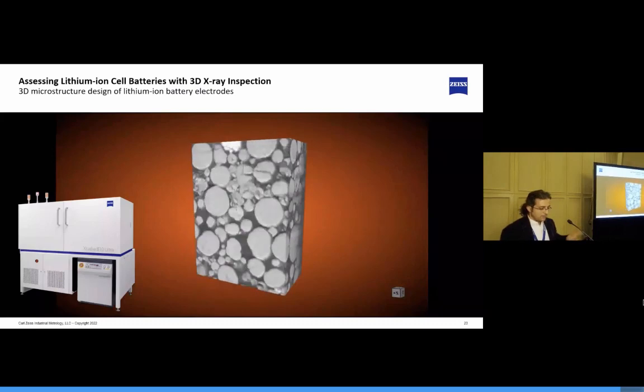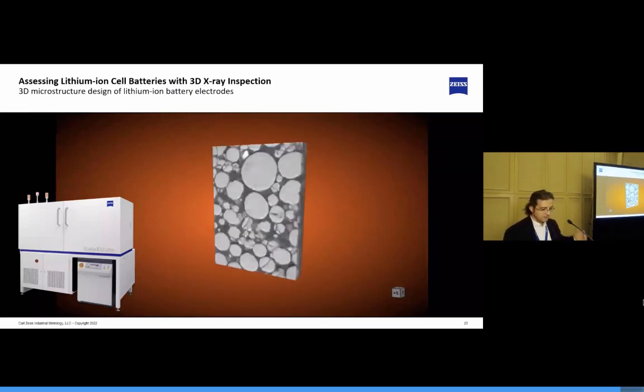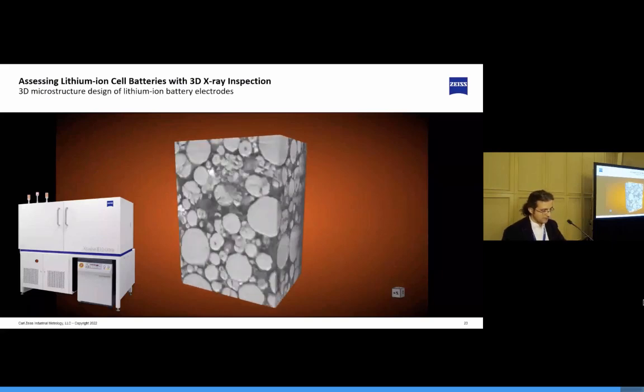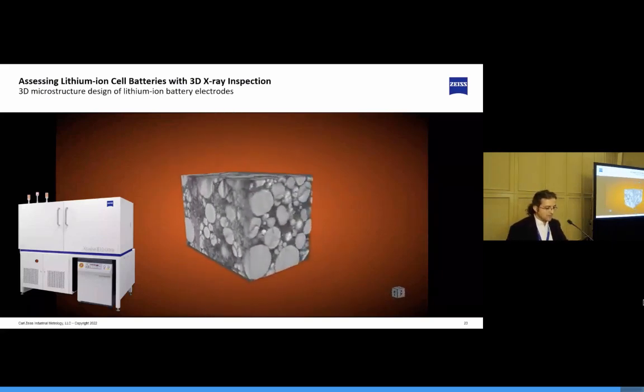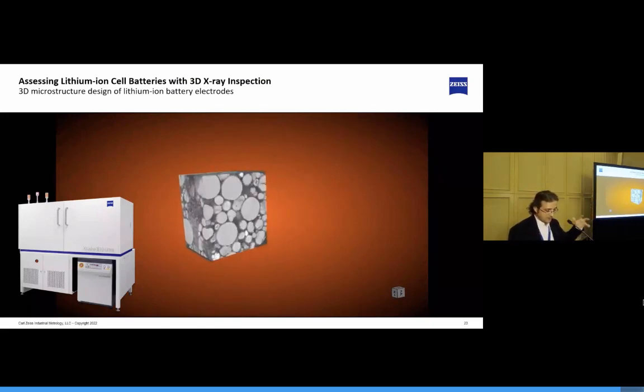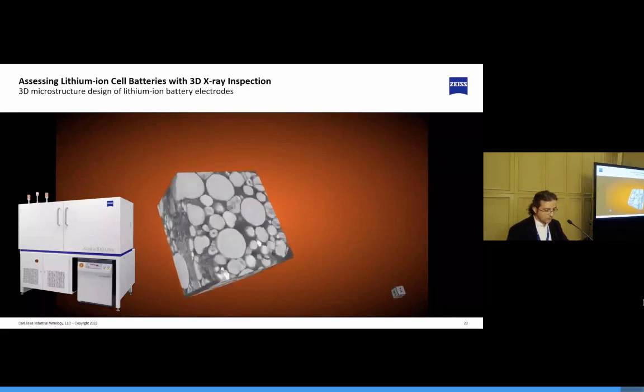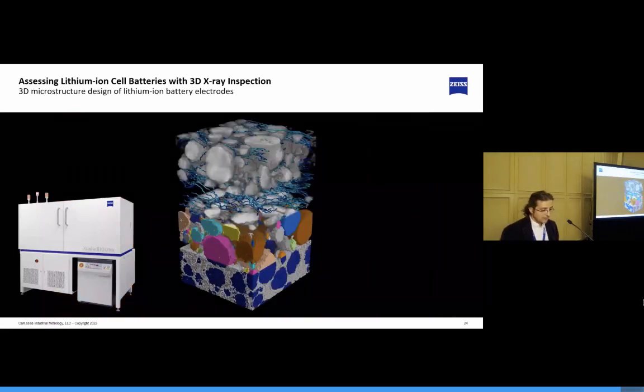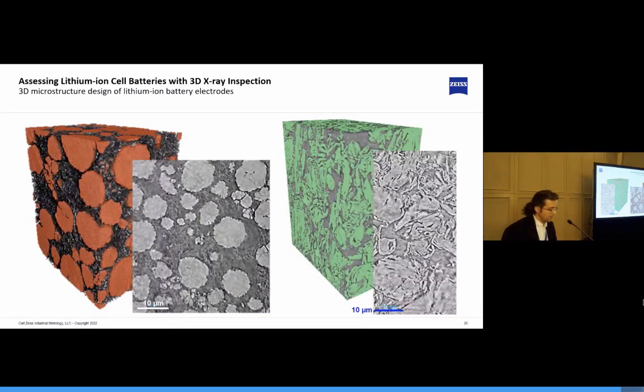And you can see the particles, the surface degradation, and some of the cracking in this image. If you want to do further analysis, you already have the data in gray levels, but you can bring this into a software to do more analysis and get some of the images of the different sizes of the particles and even see some of the dendrite structure. And those fine details, then you definitely need to do something that is called nano computer tomography to see nanometer resolutions. And you will see a small portion in this case, and you will need some sample preparation.